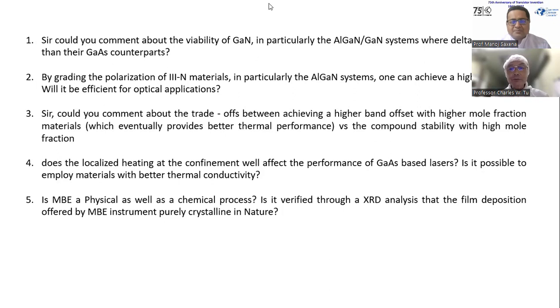Is it verified through XRD, the film deposition? Yes, so we can monitor our crystallinity by electron diffraction in situ, inside the machine. We have an electron beam, and then we look at the diffraction pattern. So we can do it in situ by electron diffraction, and we can take the sample out. We look at X-ray diffraction, and we should see these X-ray peaks, but also Pendellosung fringes, all this interference due to these multiple layers.